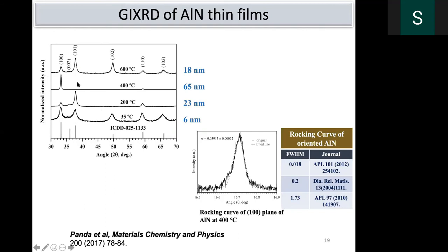And when you grow with different substrate temperatures, you can understand that at around 400 degrees centigrade, only one peak is observed around 100, but the remaining peaks are almost nil. That's very important. And we did analysis of the rocking curve. The rocking curve basically tells whether the material is single crystal or not. That we can find out from the rocking curve.